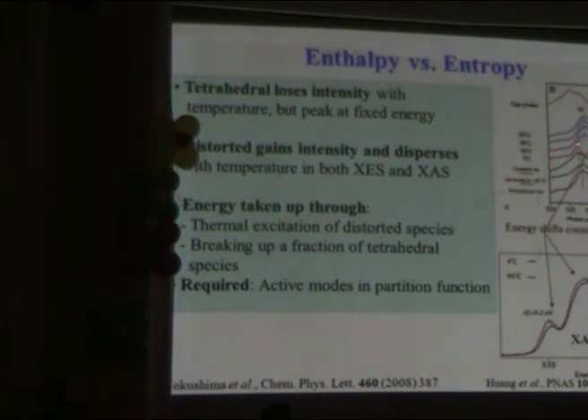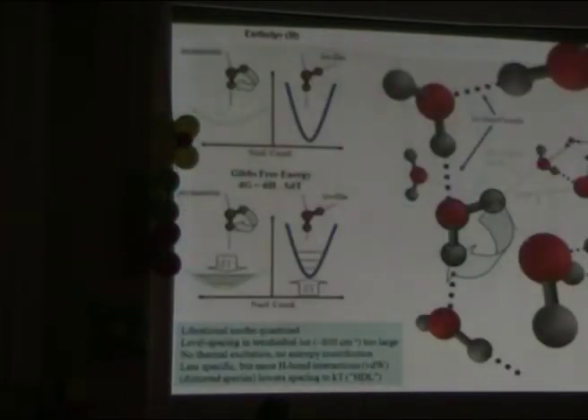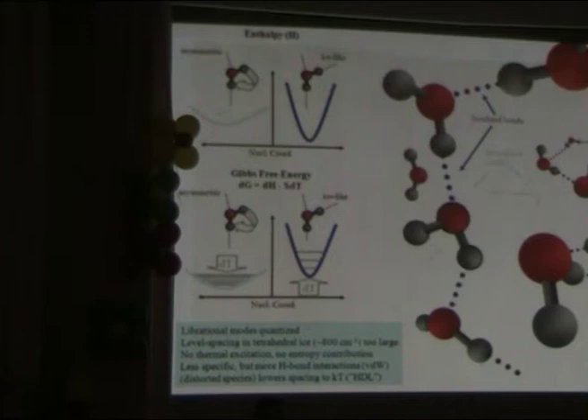We convert from this type of structure over to this. This does not get thermally excited. This one gets thermally excited. So we can assume that this new or other component can contribute to the entropy at higher temperatures. We see similar behavior in the pre-edge and main edge in X-ray absorption, that they shift towards the gas phase. The way we interpret this is in terms of the librational excitations in the liquid.